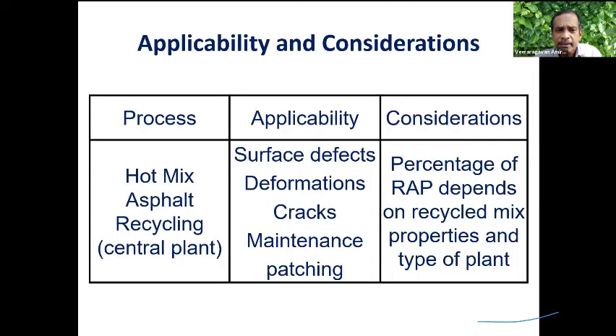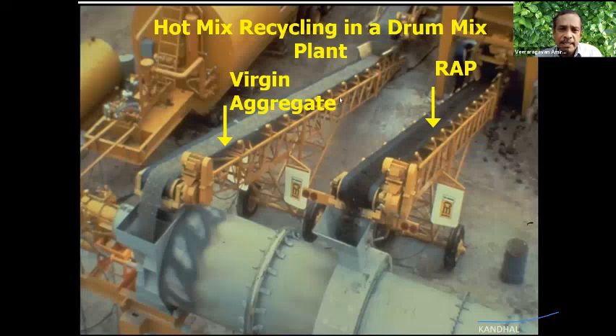Hot mix asphalt can be used when there are surface defects, as I was mentioning, the top-down cracking, deformation, cracks. But how much milled material, which I showed in a video, can be used? That again depends upon the limitations of the plant. In the case of a hot mix drum mix plant, we inject the virgin aggregate into a drum mix and use the reclaimed asphalt pavement material here. This is already aged. I don't want to heat it again.